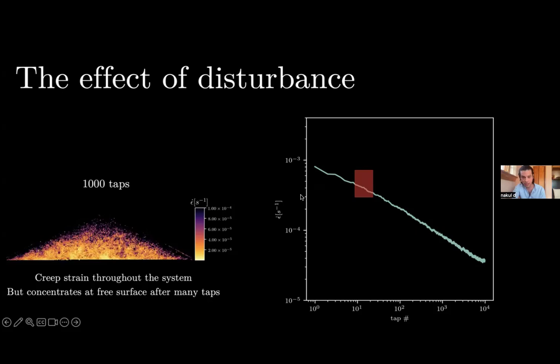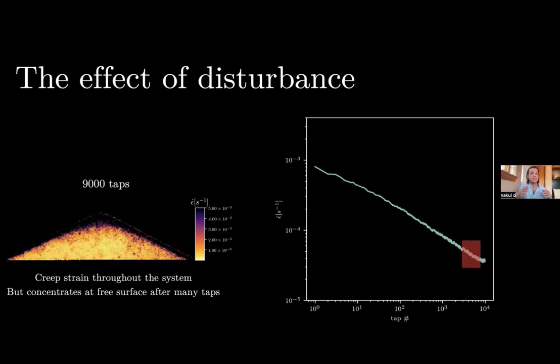So there's strain throughout the system, and it concentrates at the free surface after many taps. And I think we tapped this something like 10,000 times, and you can see that there's a strong decay of the response with increasing number of taps. So if I look at the system after it's been tapped 9000 times, most of the creep in the system has been depleted, right? Like the magnitude of these strains are much lower than those at the free surface. So as you're tapping it, the interpretation is that it's compacting in the core, and that compaction reduces creep, but the free surface is still free to dilate and respond to the agitations.